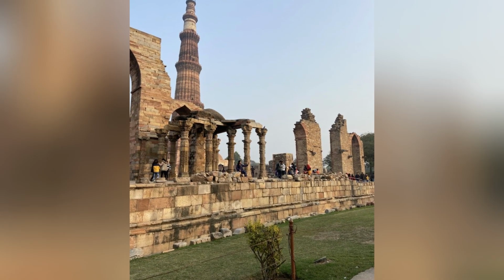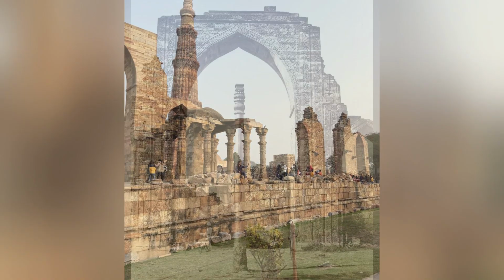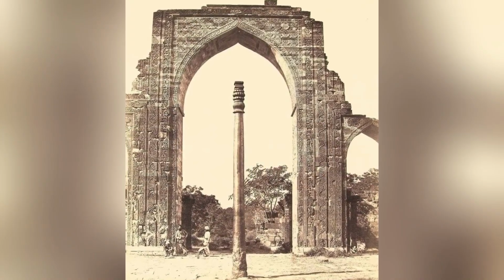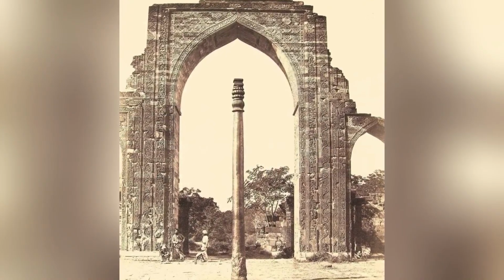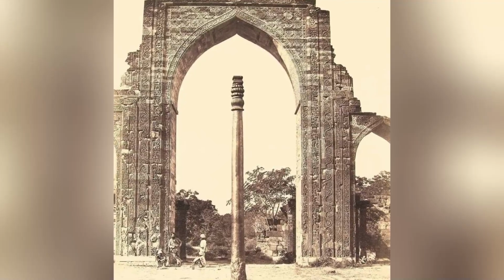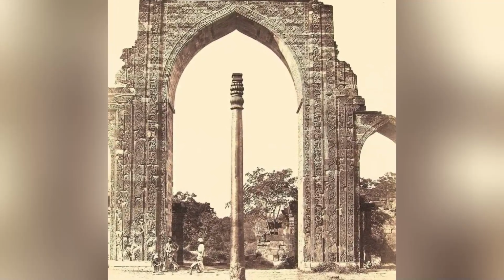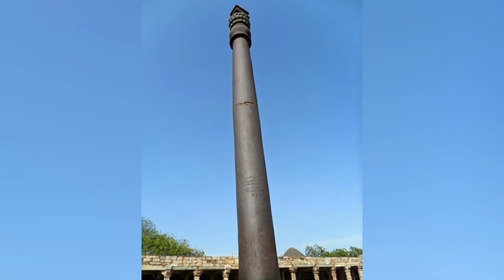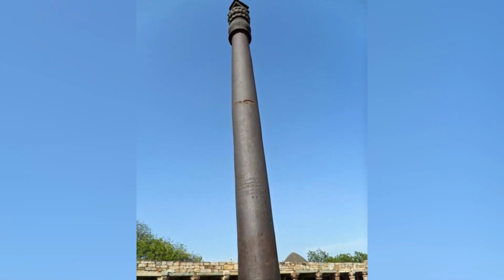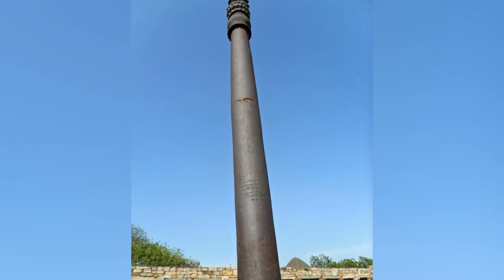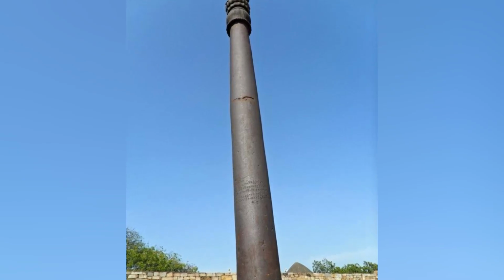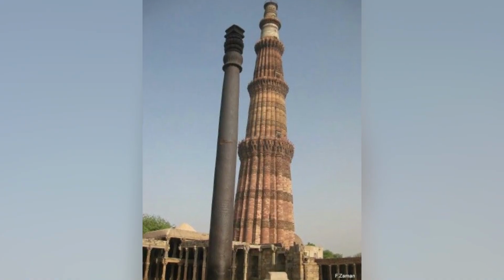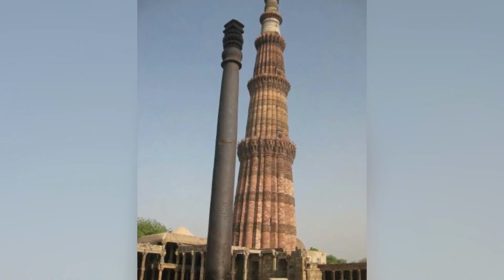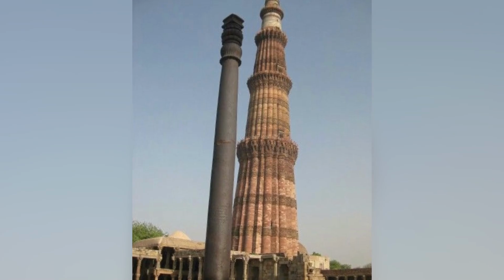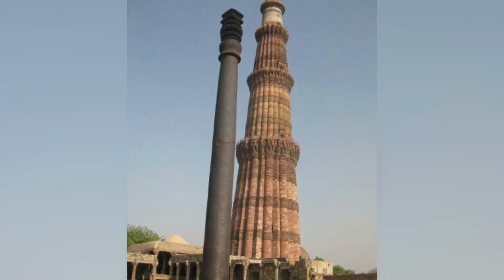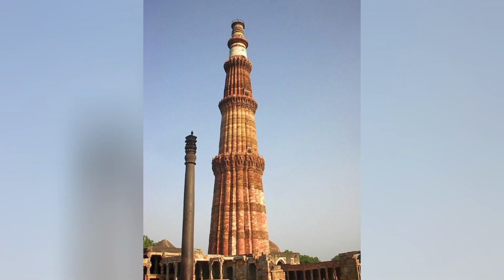The Delhi pillar's protective film grows at a rate of approximately 3/100ths of a micrometer per year. The ratio between these two rates is approximately 1500 to 3000 to 1, meaning that ordinary iron corrodes approximately 1500 to 3000 times faster than the Delhi pillar in the same environment. The difference is not a small, marginal improvement. It is a difference of several orders of magnitude, a difference that is comparable to the difference between the speed of a person walking and the speed of a commercial jet aircraft.